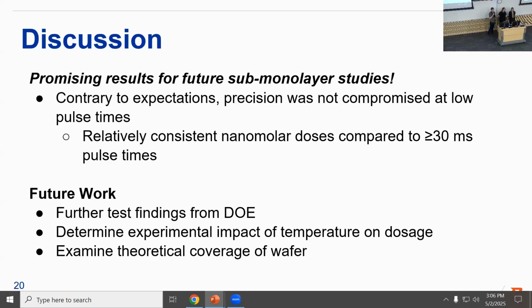Regarding these findings, this is actually quite promising for future submonolayer studies, as contrary to our expectations, the precision was not compromised at these low pulse times. This will allow us to do relatively consistent nanomolar doses at these 30 milliseconds and lower pulse times. We also found that the cross-chamber pressure was significantly more impactful than pulse time on the gas dosage. For these submonolayer studies, that's good information to have, so they can really focus on that cross-chamber pressure when they're trying to get these nanomolar doses.